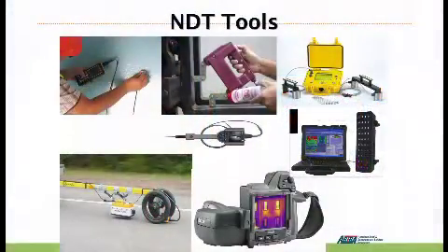Here are some of the NDT tools that I just talked about. Here's the UT, ultrasonic thickness, to measure the thickness of the steel structures. Right below it is the ground penetrating radar that we use on highways and bridges. We can run at about 45 miles an hour to collect data and process it in our office to figure out the depth of reinforcement statistically. So we can say, hey, our chloride is only 1 inch deep, our steel is 2 inch deep, so we can easily remove the chloride sitting there and be able to put a new overlay and save the structure.